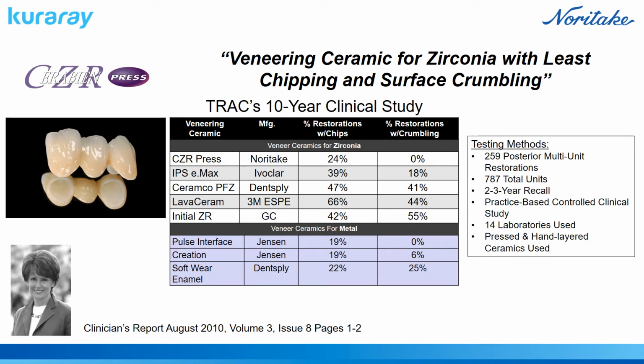Okay, so just one last thing, and I'll let you go, is that there's a 10-year clinical track study done by CRA and Rella Christensen and her colleagues there, where they take the zirconia substructures and whatever is recommended from that zirconia substructure by the manufacturer, and they use the layering ceramic on it. And this is a 10-year study done, and I believe it was published, initial report was August 2010, then they came out with a 10-year report, and the CZR press from Noritake on top of the zirconia substructures had 0 crumbling. Just like the top PFM down here, 0% crumbling.